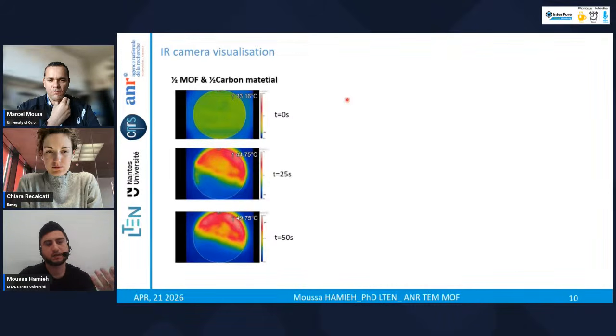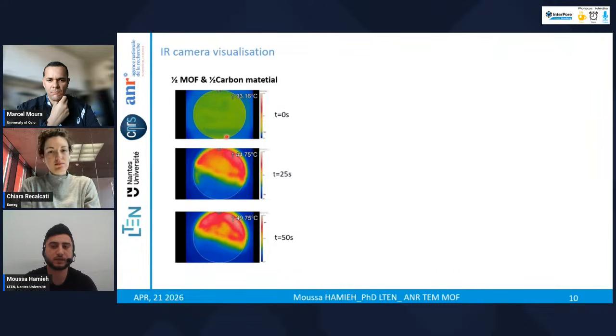Later I just wanted to visualize with a camera the increase in temperature. Here we are talking only about the first experiments. Here it was the support of aluminium. I put half MOF and half the carbon material. And for sure, after activation, I injected the CO2. And as expected, we see that only the part of the MOF is heated and not the part of the carbon.